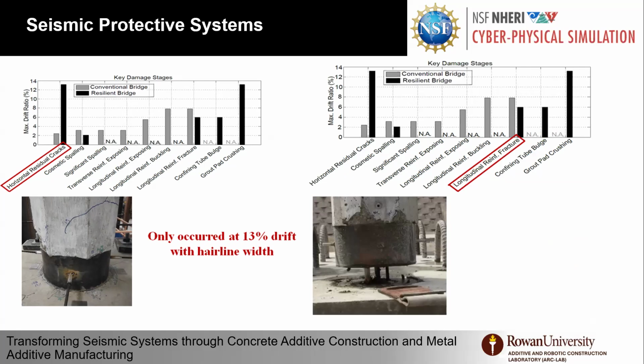We did a lot of post-processing tests using low cycle fatigue and acoustic emission to identify the fracture. However, we tried to verify that, so we saw cut all the connections, and you can see here all the outer rebar fractured, and that was a really big setback because we try to make sure that we can have a resilient system that resumes functionality quickly. It was good for the purpose of emergency vehicles because the bridge is still standing. However, after recovery, you have to replace it.